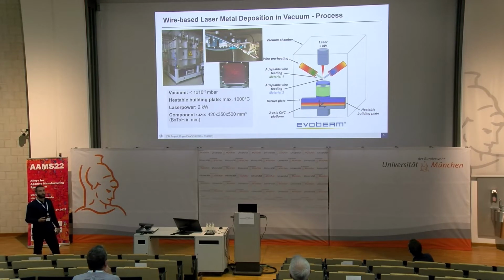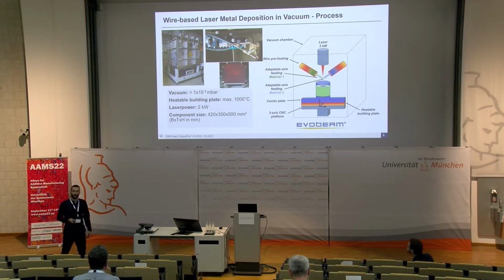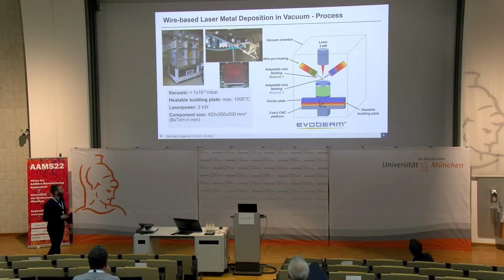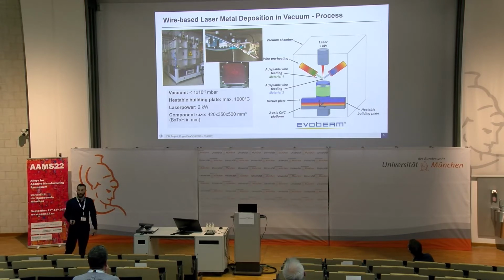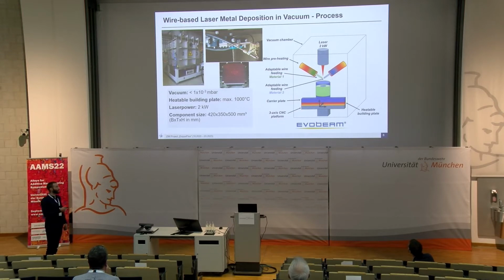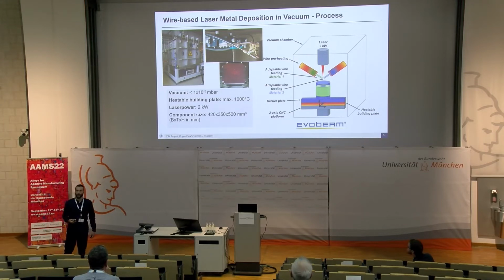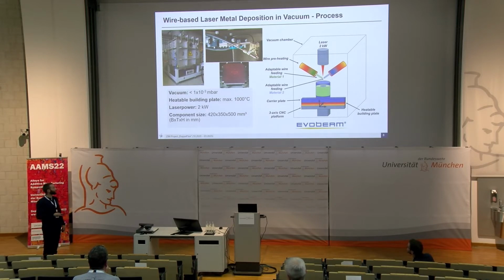So now I'm going to tell you more about the process we have at Neue Materialien Bayreuth. First, we have a vacuum chamber, and we are working with a pre-vacuum. That is enough to keep all the oxides out of the process. We also have 2 wire feeders, which are working with 1 pure aluminium wire and 1 pure titanium wire. And we have a wire preheating of these wires. It's inductive, so it works with a current. We have a carrier plate and also a heatable building plate, which arrived 2 months ago. And for the process, we have a 3-axis CNC platform. You see the maximum component size here without the heatable building plate, and we can heat the building plate up to 1000 degrees.